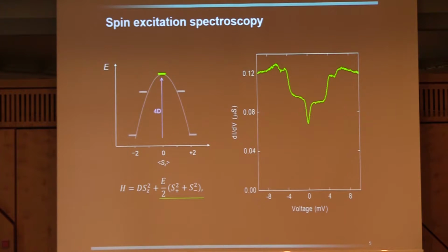But the iron atom has this transverse anisotropy that is quadratic, at least in lowest order that we can use here. And what that does to the iron atom is it mixes all these states that are right and left of this barrier into non-magnetic states, like symmetric and antisymmetric superpositions, and they all have 0 expectation value of the spin by themselves. So the iron atom itself on a surface is non-magnetic, or at least on this surface it is non-magnetic.